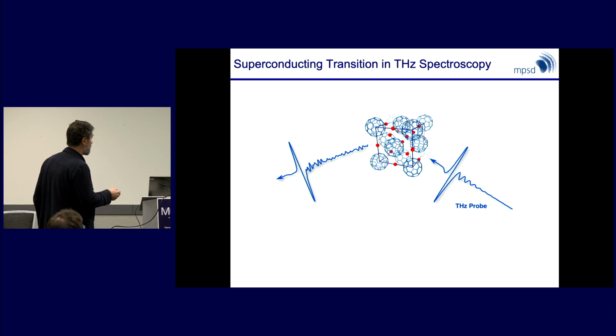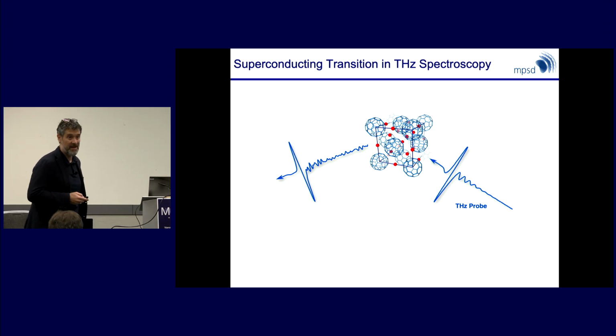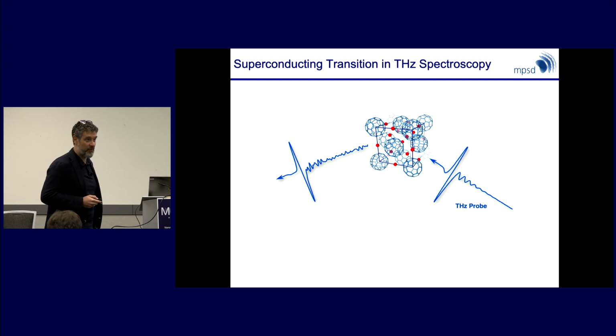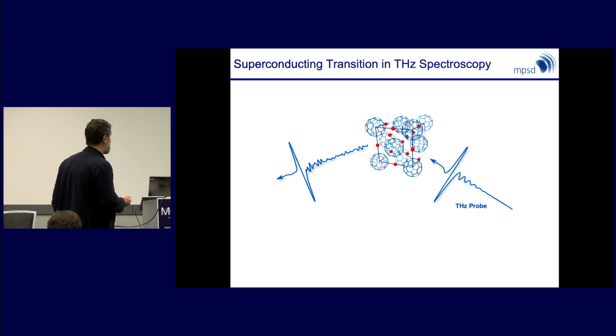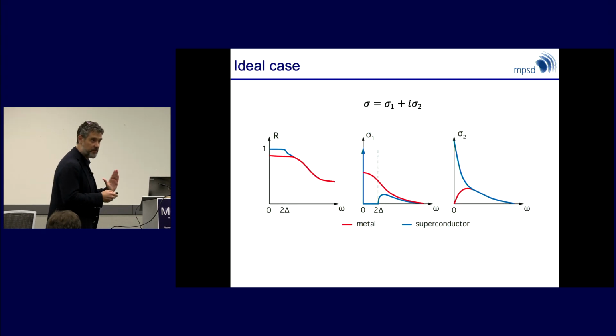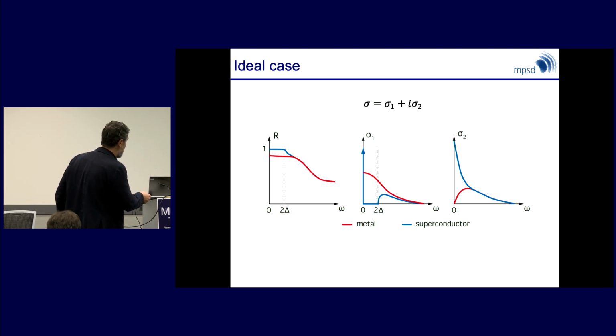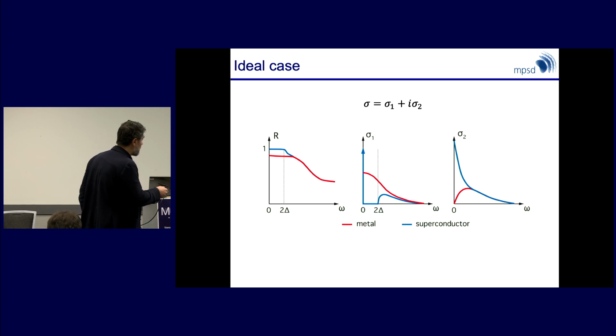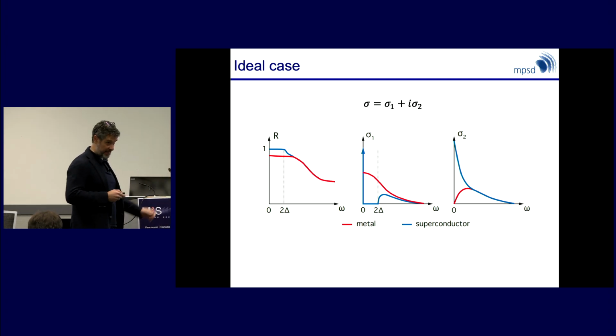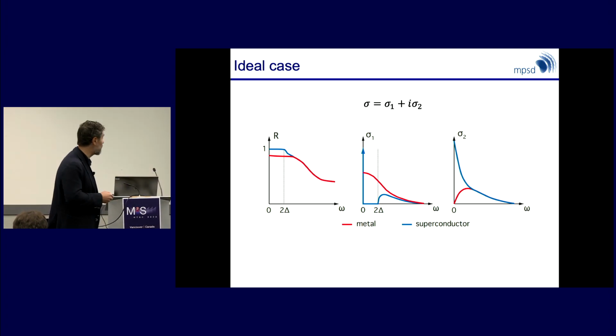So if you now measure the reflection coefficient with amplitude and phase in equilibrium of C60, and you reconstruct the real and the imaginary part of the optical conductivity, what you expect from textbooks is the following phenomenon. You have a delta function, you have a superconducting gap. At temperatures below Tc, the reflection coefficient in equilibrium should become exactly 1 for all frequencies below 2 delta. The real part of the optical conductivity, that's the in-phase response of the current to the electric field,